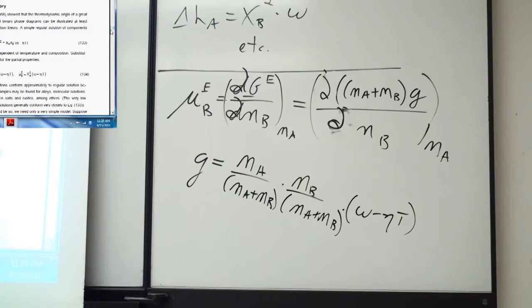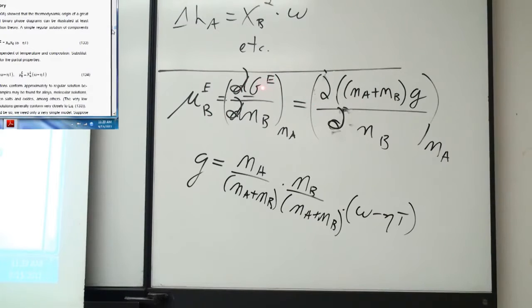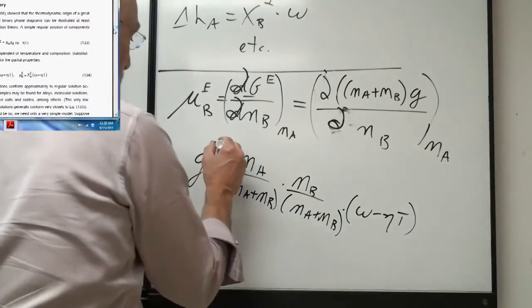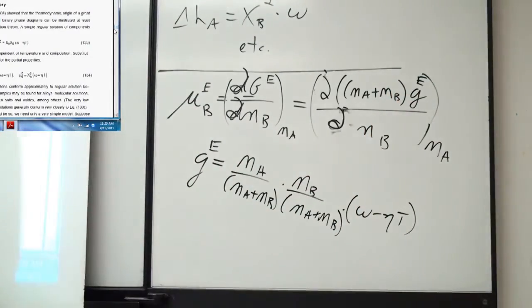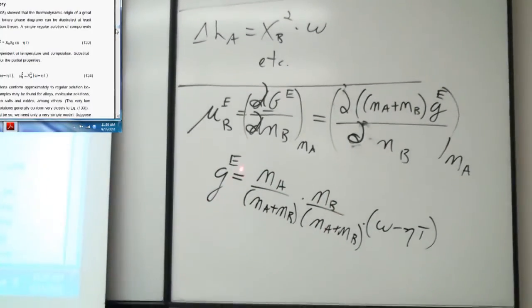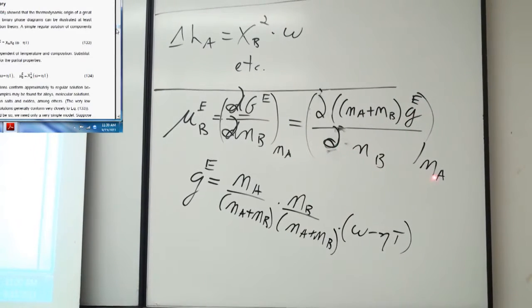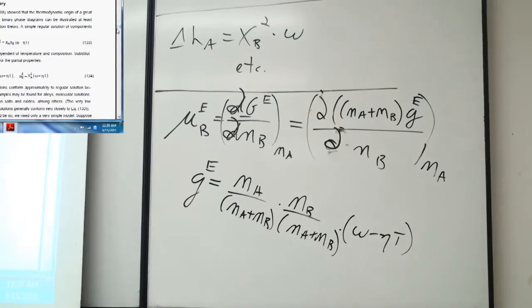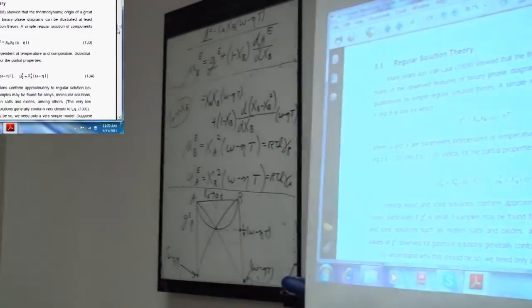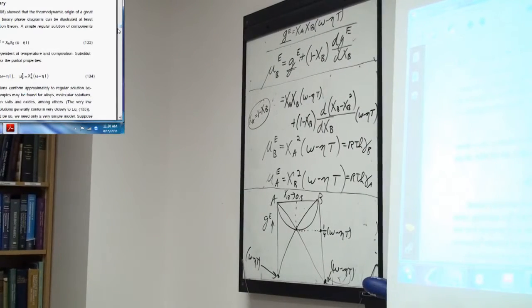Okay, so what you've got to do then is, that's the definition of mu excess B, the dG dNb. You make your total excess Gibbs energy the total number of moles times the molar excess Gibbs energy. And the molar excess Gibbs energy then is given by this equation, XaXb times omega minus eta T, where Xa is Na over Na plus Nb and Xb is Nb over Na plus Nb. So you take this equation for gxs, substitute it into here, do the partial differentiation, keeping Na constant, and you should end up with the same equation. So to have a little practice using this kind of stuff, I recommend you try that. It'll take you 2 minutes.